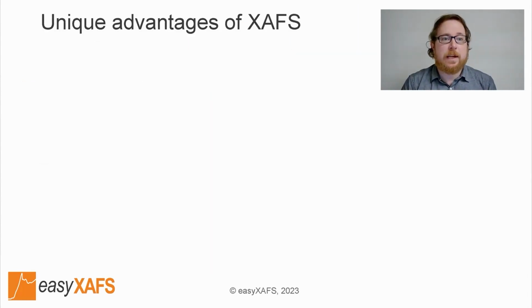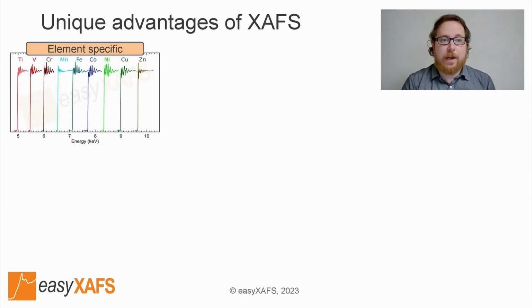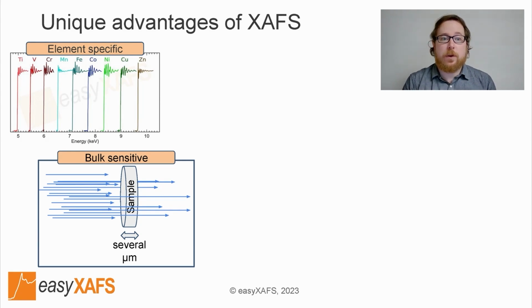As I mentioned previously, XAS provides some unique advantages when it comes to materials characterization. First, because the fine structure occurs specifically at energies around the binding energy of a core electron, and different elements have different characteristic binding energies, XAS itself is an inherently element-specific probe. What this means is you can have a whole mix of elements in your material, and you can probe the chemical state of each one individually. Second, the use of hard X-rays means that it's a bulk-sensitive technique on the scale of several to tens of microns. This makes it a good complement to more surface-sensitive techniques, such as, for example, XPS.